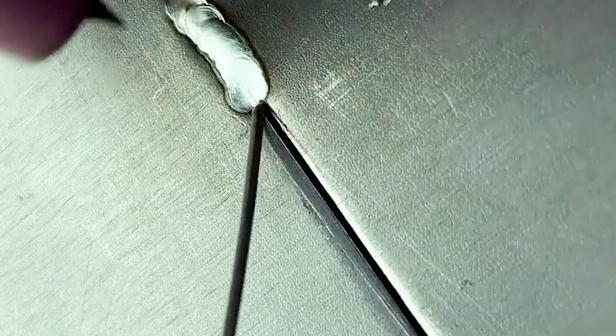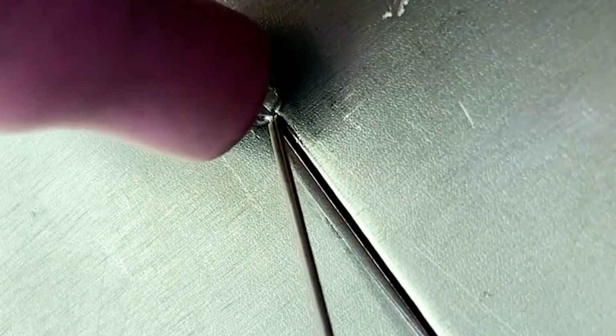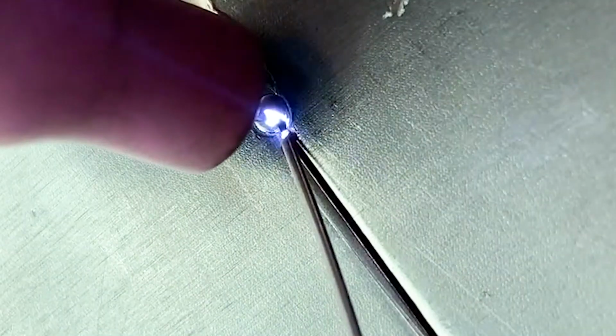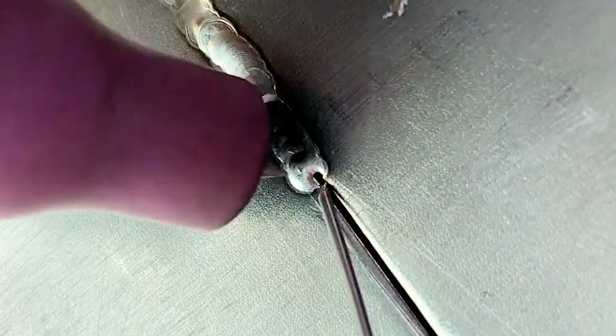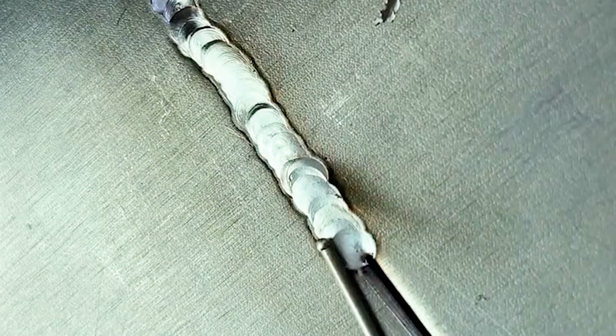The cold welding machine is suitable for repair welding of various parts, and it is not restricted by the tabletop and can be quickly used without experience. For example, dents, holes in the plane of the substrate, crevices, grooves and scratches after abrasion, edges and corners, corrugated lines, sharp peaks, cracks, collapses, pores, trachoma, porosity, and the argon welding undercut problem after welding, thin stainless steel and thin iron less than 0.1, copper, aluminum and other thin plates less than 0.1, and welding repairs for defects in nitrided workpieces.